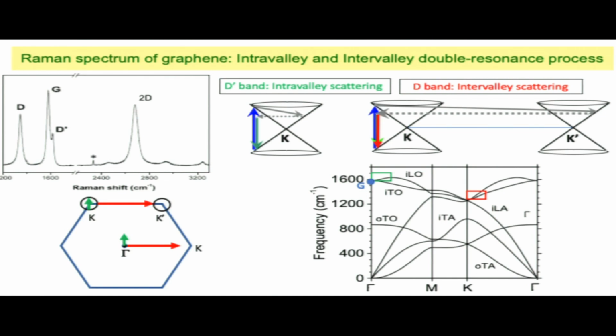But then you can see that what we call the inter-valley scattering involves phonons that are close to the K point in the phonon dispersion. That's why the frequency is here at 1350 wave numbers. And the D prime is the band that comes from this branch here. That's why its position is a little bit above the G band.